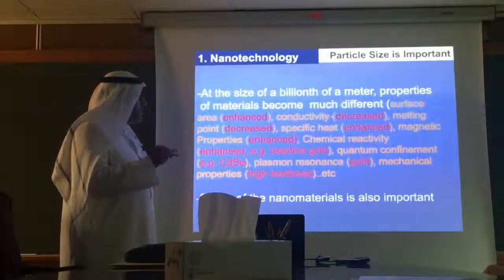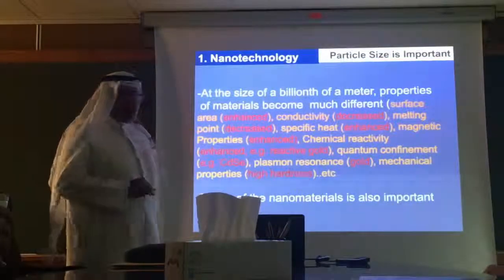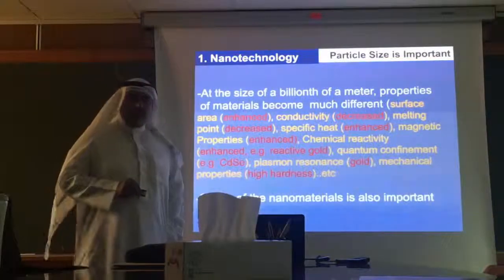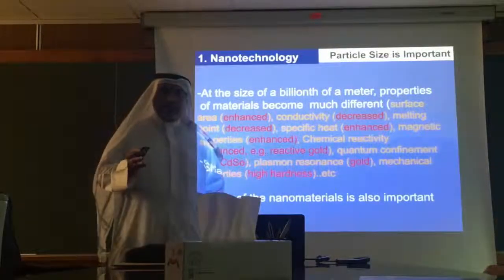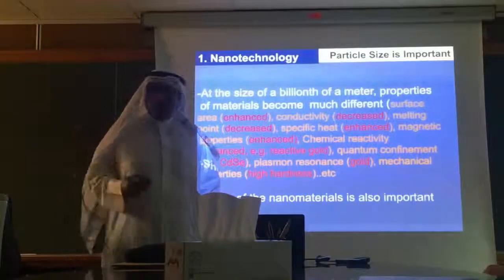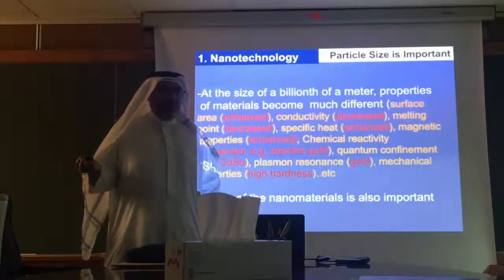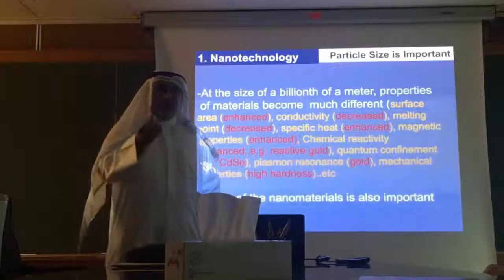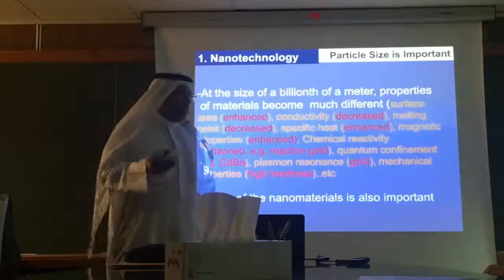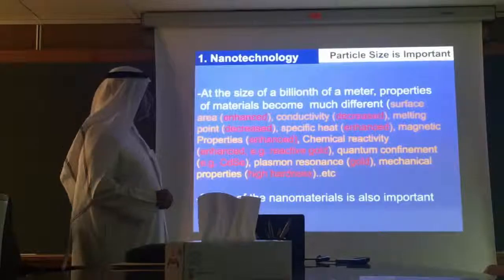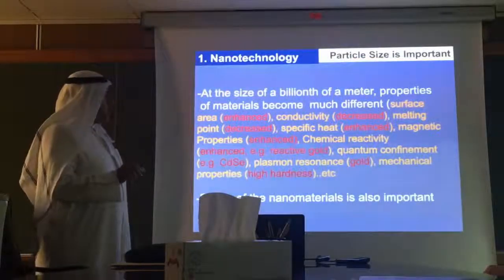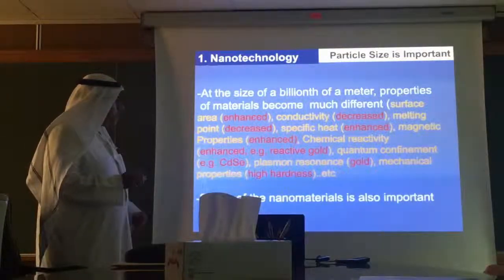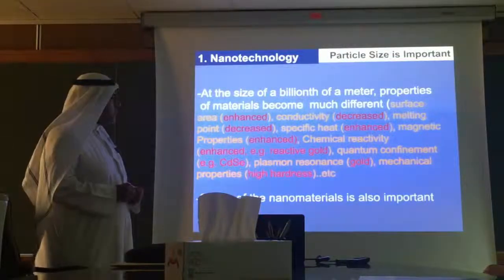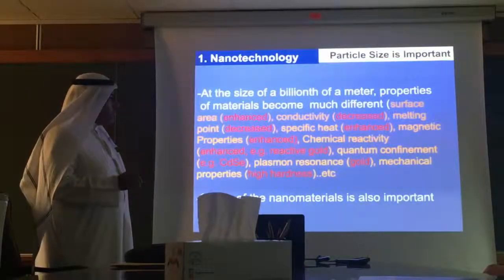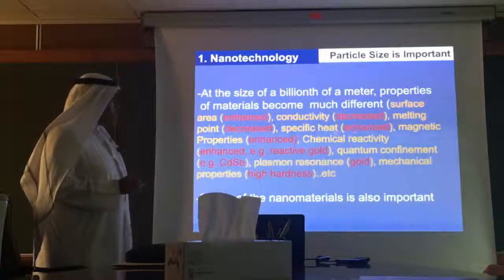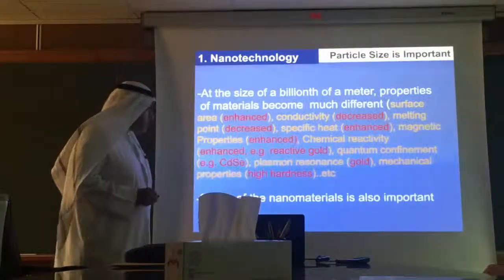The conductivity of some of the material actually decreases by decreasing the size of the nanoparticles. If you have conductive material, you can make it semiconductor by decreasing its size. So we have silicon, the famous semiconductor, but now I can make copper semiconductors by decreasing its size, or iron semiconductors by decreasing its size. The melting point also decreases by decreasing the size of the particles. The specific heat is also enhanced, the magnetic properties enhanced, the chemical reactivity enhanced,